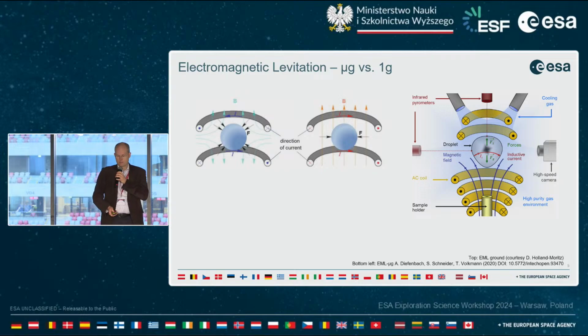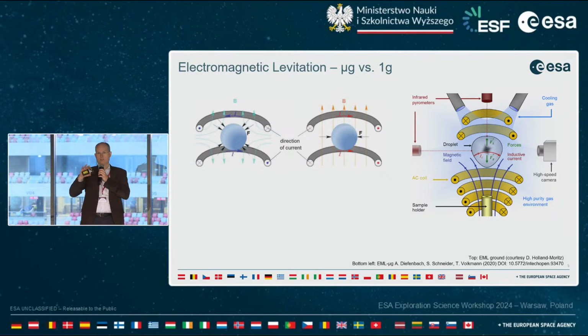So how does it work? You might not have seen this before. It's basically having a spherical sample freely floating. If you do that on ground, that's on the right-hand side, you see kind of a deformed droplet. This is because you need a relatively high magnetic field in order to lift the sample against gravity, and at the same time it is heated by this electromagnetic field. So you have a coupling between the lifting force and the heating in this case, and the heating also drives a lot of convection inside of the sample.